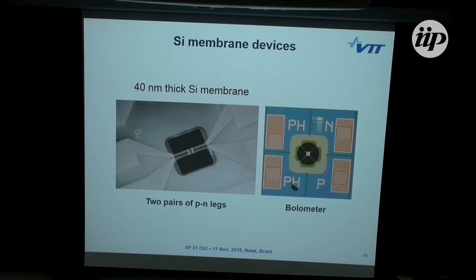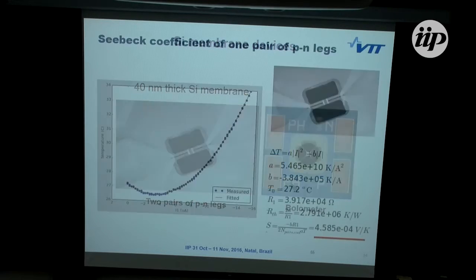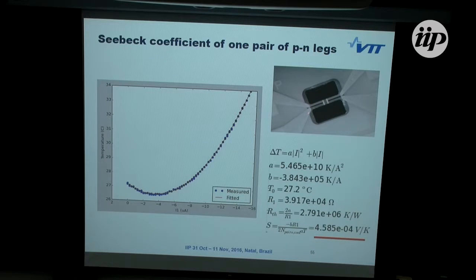And this is a picture of the bolometer. Using this one, one starts to run current through these two pairs, and uses the other end as a thermometer. First, the Peltier effect sets in, so the temperature goes down, and then Joule heating hits in, and then it starts to increase. So one can fit this and get from there the Seebeck coefficient for a pair of legs.